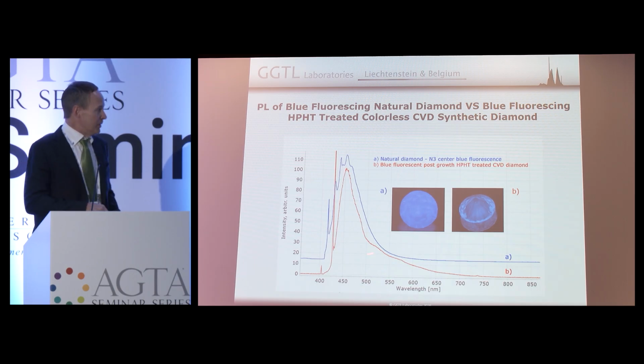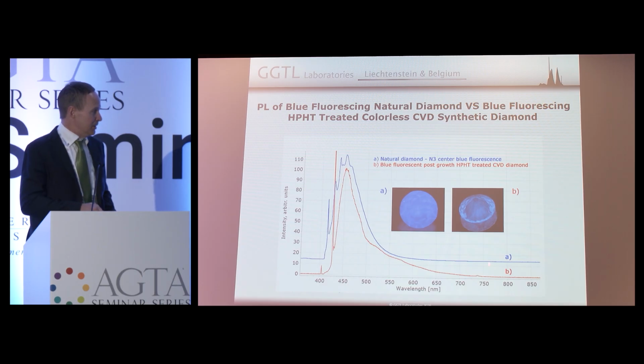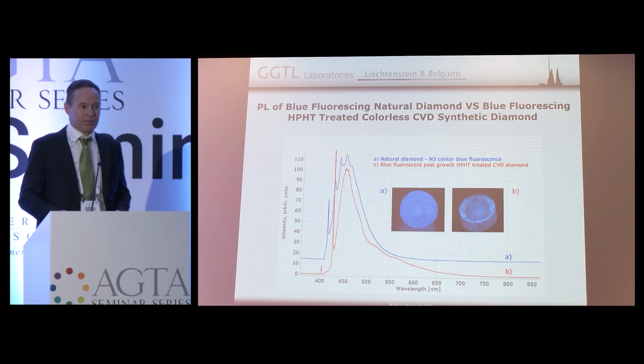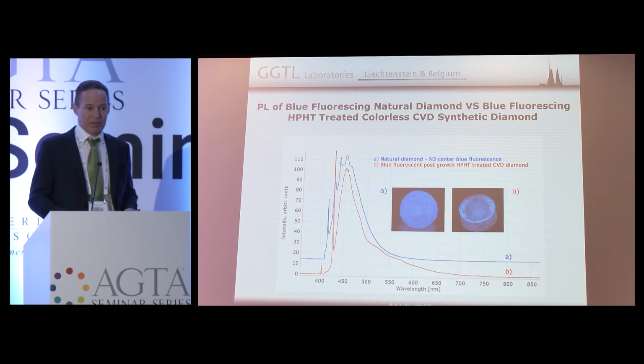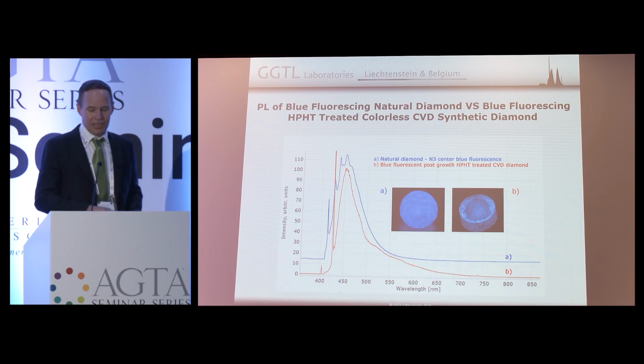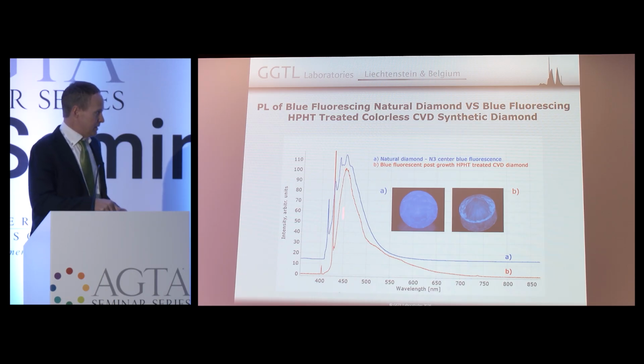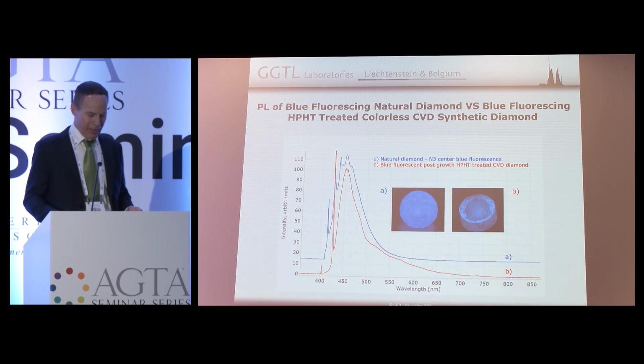You can see the CVD synthetic diamond spectrum at room temperature is just a broad band. Here you see the N3 center at room temperature, and this broad band is responsible for your blue fluorescence. But with a small, not very expensive spectrometer and a 405 laser, you can visualize this really easily. So this distinguishes them by spectroscopy right away.